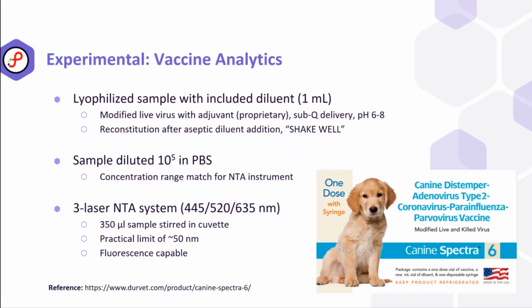Now, a couple of things about the 3-laser system. Why do we need more than one laser? Well, if you look into the Rayleigh equation, the scattered intensity off a particle is proportional to 1 over the wavelength to the 4th power. So as we go lower in wavelength, we get better scattering. So at 635, we can measure larger particles and probably down to the 100 to 200 nanometer range. 520 fills in some of that as well.